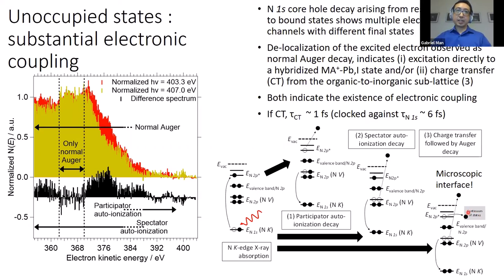So this finding shows that the unoccupied states are strongly coupled, and suggests that the picture of an electronically inert A cation is not quite correct.